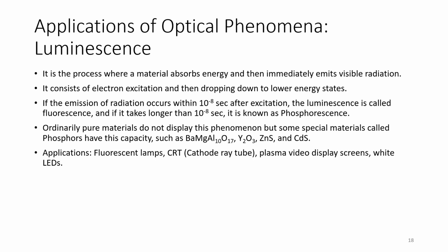Ordinarily, pure materials do not display this phenomenon, but some special materials called phosphors have this capacity, such as zinc sulfide and cadmium sulfide. Their applications include fluorescent lamps, CRTs, plasma video display screens and white LEDs.